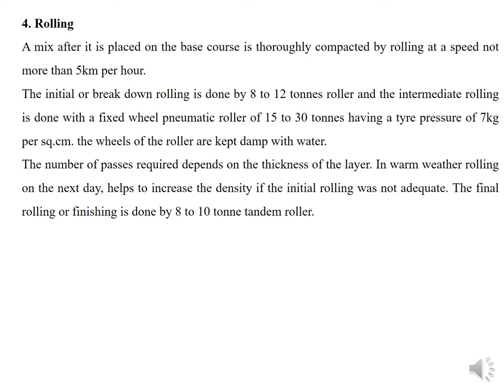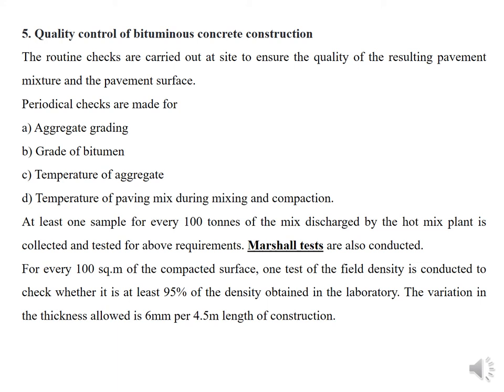Step five is quality control of bituminous concrete construction. At every stage you have to maintain quality. Routine checkup means whenever the bituminous concrete is ready, you have to check: aggregate grading, grade of bitumen, temperature of aggregate, and temperature of paving mix during mixing and compaction. In the hot mix plant, you have to check the properties of the aggregate and temperature as part of routine checkup.